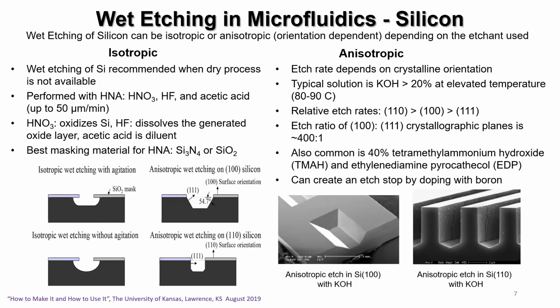However, if you do potassium hydroxide, 20% potassium hydroxide, greater than 20%, at elevated temperatures, 80 to 90 degrees, look what happens. Now you're getting anisotropic etching just by simply changing the chemicals. It's still silicon, and this is silicon 110. That's the crystallographic face of that material. These are single crystalline materials in this particular case. And I hope I don't have to go through and explain that. If you're a chemist, you know what that is, but they'll tell you what this is. But look at the etch rates. It's different. 110, 100, 111. It'll etch in potassium hydroxide at different rates to create these structures. So this is why silicon is so attractive, because of the single crystal nature of it, and the fact that you can select either isotropic or anisotropic etching.